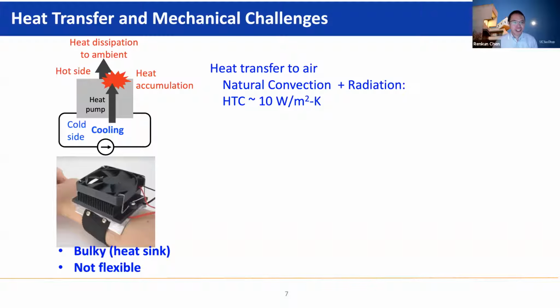So if you want to put a thermoelectric device onto our skin for cooling, if you look more carefully, you are actually looking at two big problems. One is, this is what people have traditionally done in the past. If you have a thermoelectric device, you need to put it on the skin, and it's very bulky. The main reason it's very bulky is you need an active heat sink, because you need to eventually dissipate heat from the hot side to the environment. But when the environment is very hot, like 37 degrees Celsius, you need this hot side to be at a higher temperature than the environmental temperature, for example, 40 Celsius. Then you also want to dissipate heat from the hot side to the environment. That's why most of the time you need an active heat sink like a fan.